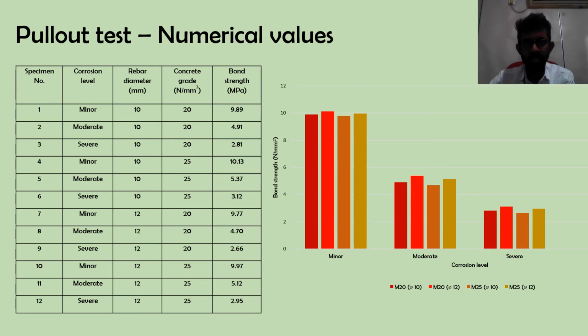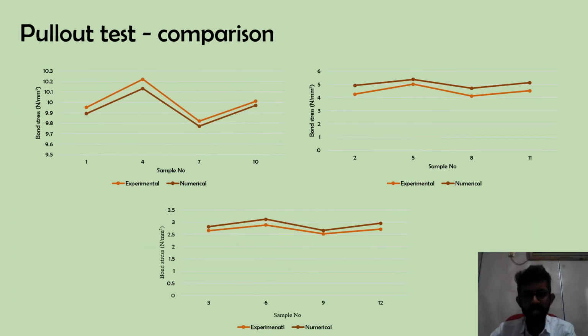The results obtained relevant to different specimens from the finite element analysis are shown in the given table. When comparing the variations of the experimental and numerical values, they show likely the same trend of variation except the values relevant to the control samples. Numerical values of bond strength for moderate and severe corrosion levels are higher than the experimental values.